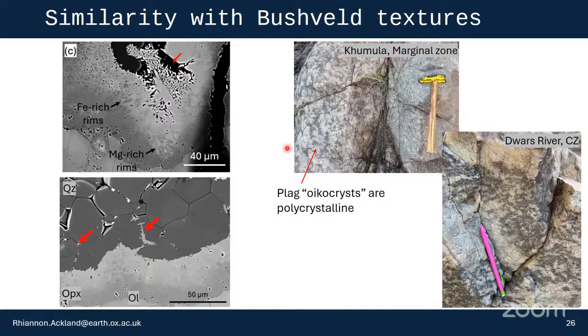Yeah, and then I just wanted to finish on raising some points of similarity between the experiments that I've done and some of the textures that we've seen during our Bushveld fieldwork over the last 2 weeks. Firstly, as I mentioned, you get complete overprinting of the primary textures in my experiments with these very polycrystalline orthopyroxene rims. And one of the outcrops we saw of the marginal zone had what looked like beautiful large plagioclase oikocrysts, but actually they're very finely polycrystalline, much in the same way, so potentially completely recrystallized, and you've lost that primary magmatic texture. And secondly, I see that it's possible to get migration along grain boundaries, even away from the original interface.